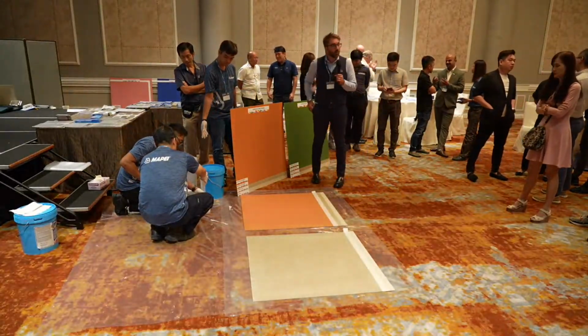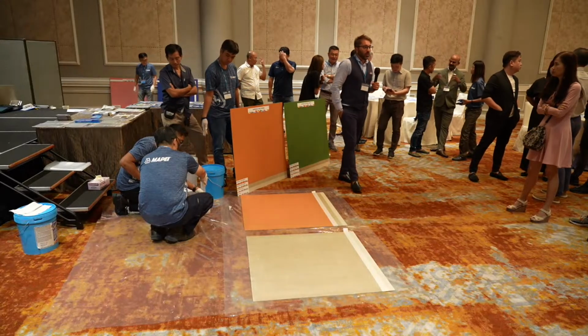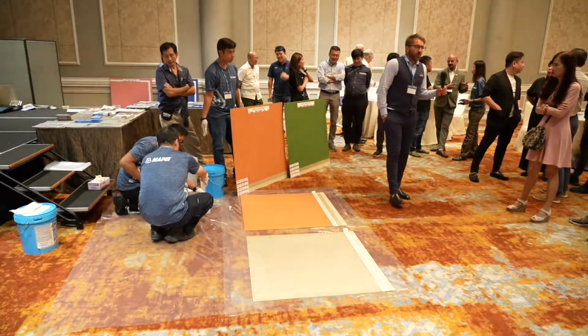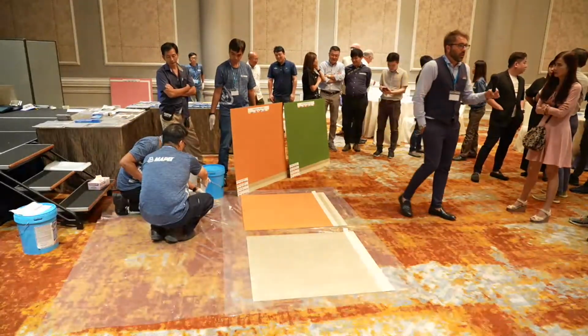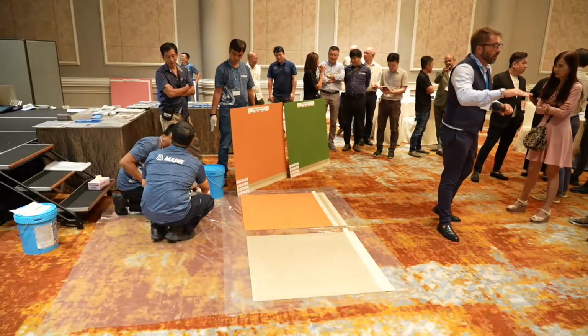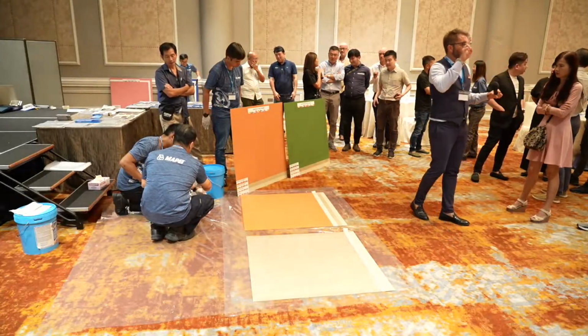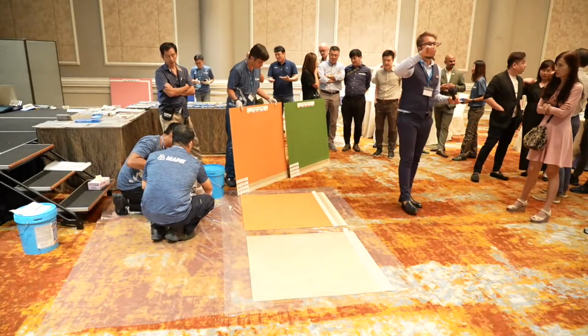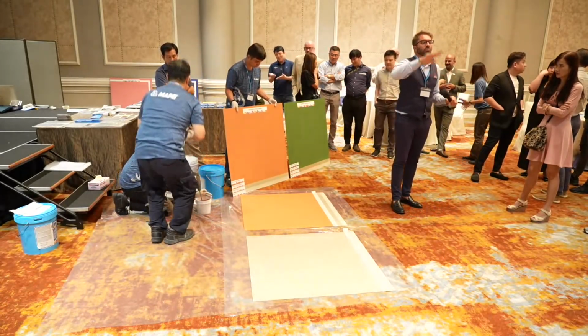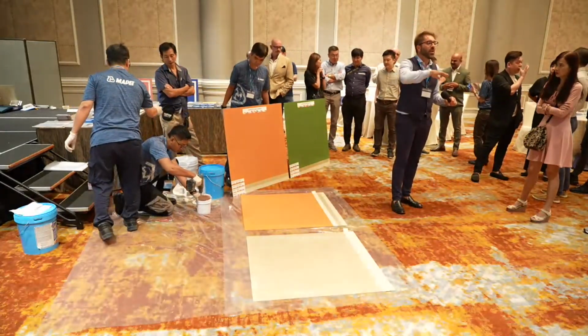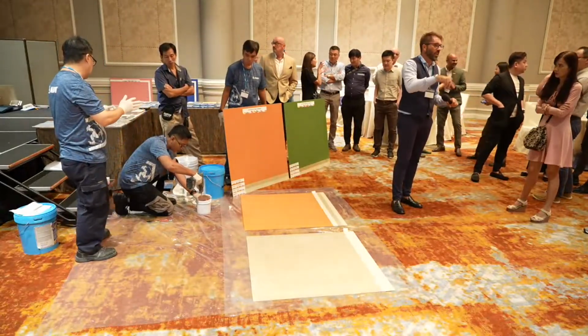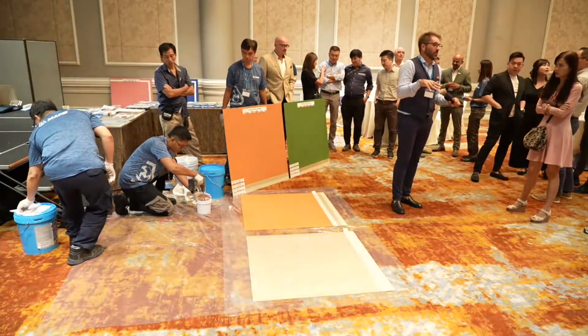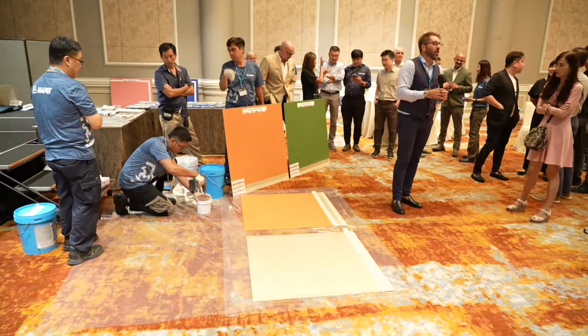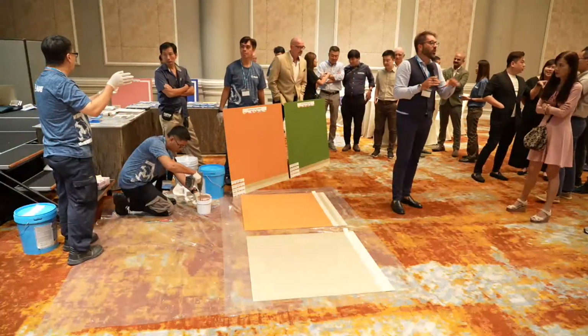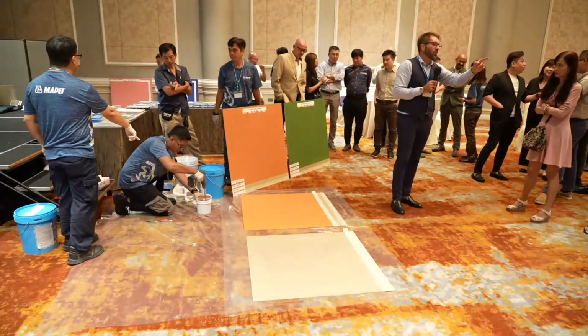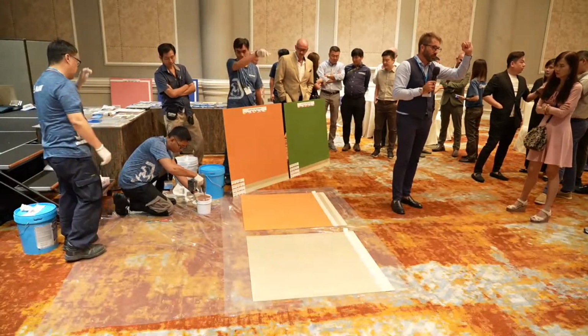So what would you do for high humidity? Less water or more water? For high humidity, I prefer a medium level. It means if the range is from 5 to 15, then with high humidity like you have here, 10% of water should be the right one. Because combined with high humidity, we also have high temperature.